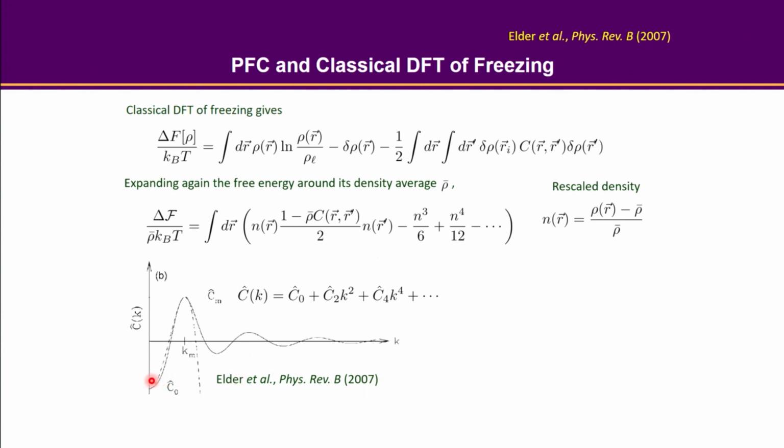So in this paper, basically they fit the correlation function in the reciprocal space with this quartic polynomial. All right, and there is a certain constraint on the signs of those three coefficients. C0, C2, and C4 are three numbers, and since at k equals 0 the structure factor would have a negative C0, C0 has to be negative. But when k increases, you start to see an increase in this function, which means C2 has to be positive. And of course, we only model the first peak, and this function goes down at larger k, so you will need C4 to be negative.